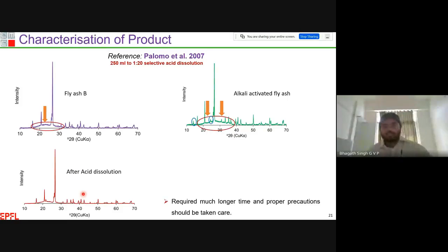Okay, fine. Thank you. Yeah, this is after acid dissolution. This is the existing methodology I have used to see whether it will dissolve only the reaction product or also the glassy phases present in our fly ashes. And the existing methodology dissolves only the amorphous reaction product as well as the new crystalline phases without affecting the glassy phase of the fly ash. That was evident from the XRD signature.